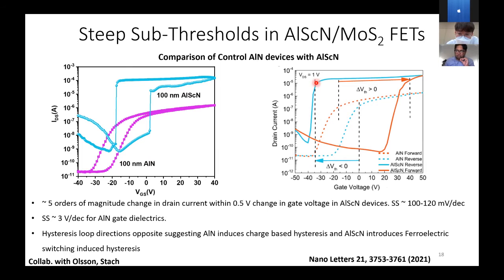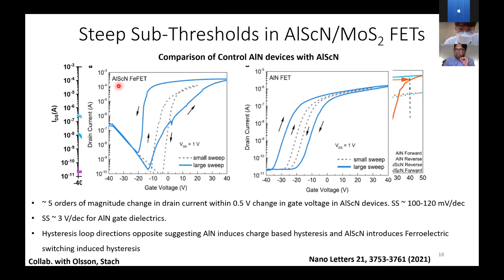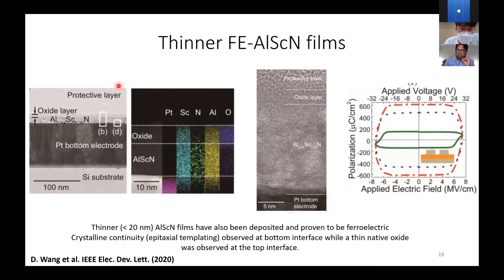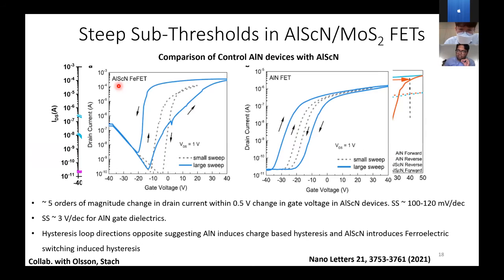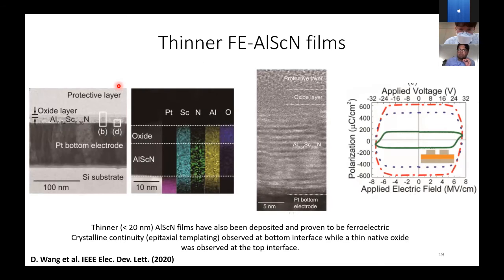The other thing to notice is that the switching slopes in the ferroelectric FETs are very, very steep. Right. In fact, if you look at this one, the switching slope is very steep, about 100 to 120 millivolt per decade, as compared to about 3 volts per decade for aluminum nitride. This further tells you that you have this ferroelectric switching going on, which produces an effect known as negative capacitance. And this negative capacitance effect can give you this kind of very steep switching behavior.